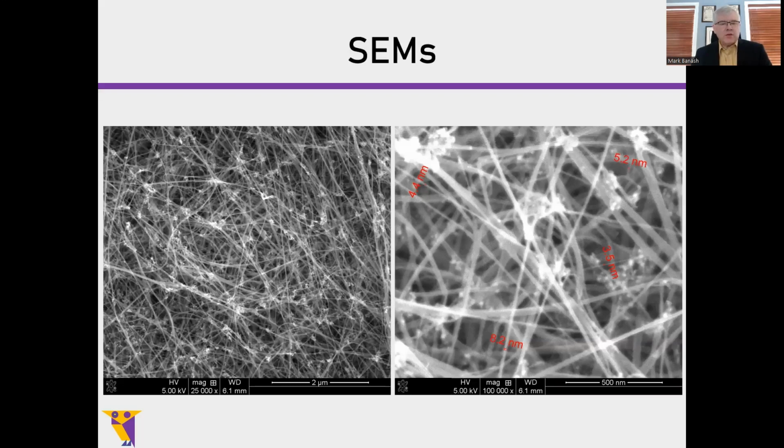If you take a look here, these are SEMs of a typical multi-wall nanotube product. These tubes have lengths in the millimeter range. And if you look on the one side where you see the measurements, you can see that these tubes are long, fairly straight, and have diameters in the 3 to 8 to 10 nanometer range. So these are a fairly typical multi-wall product with the right size diameters. But note the structure, note the morphology. Note that these things are straight.